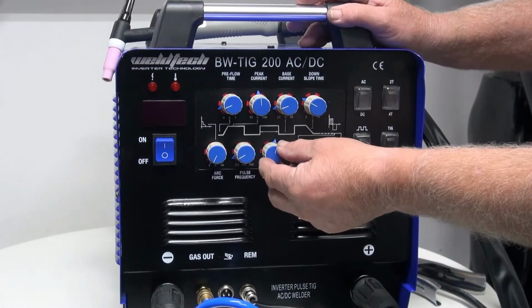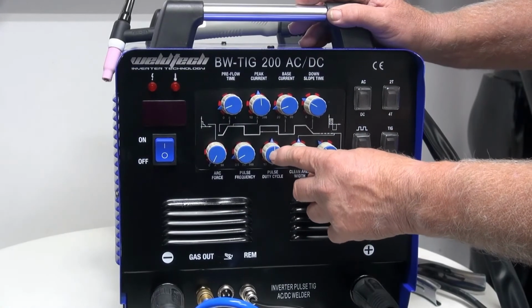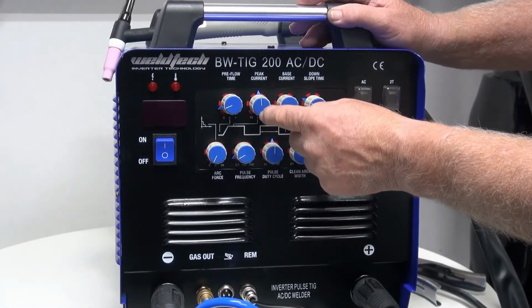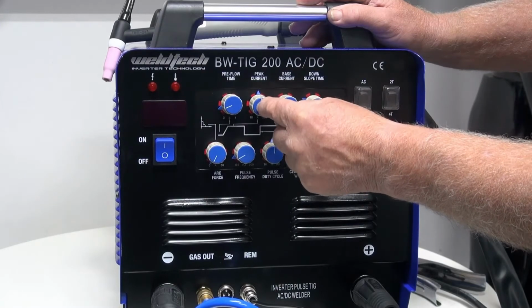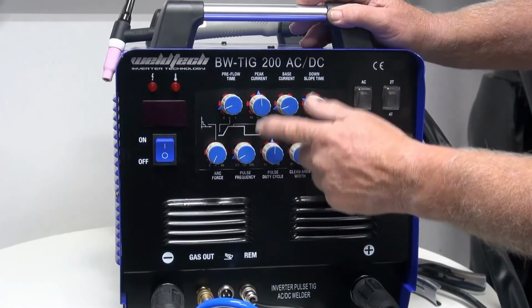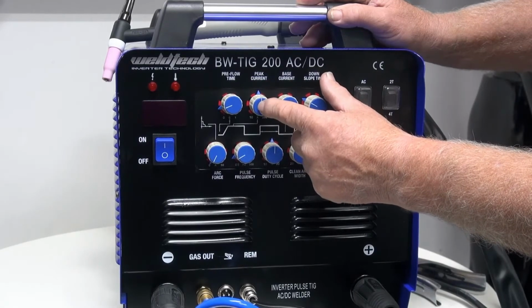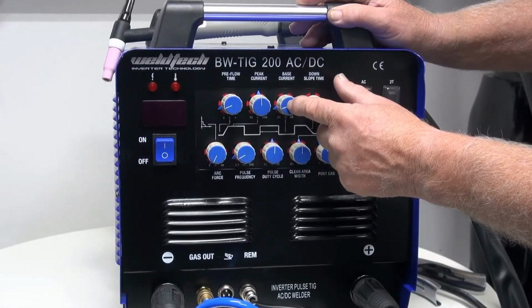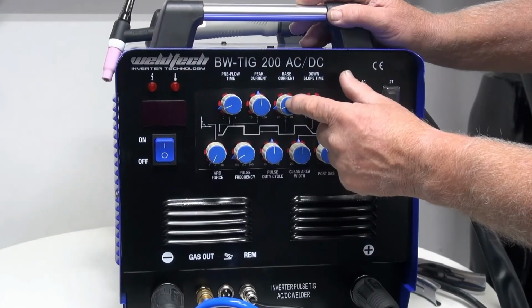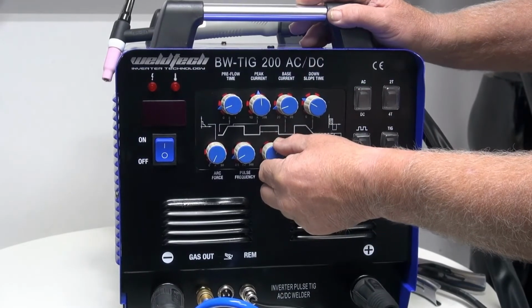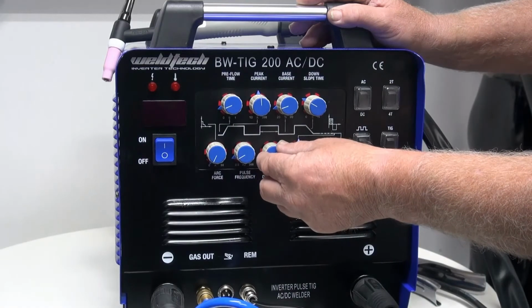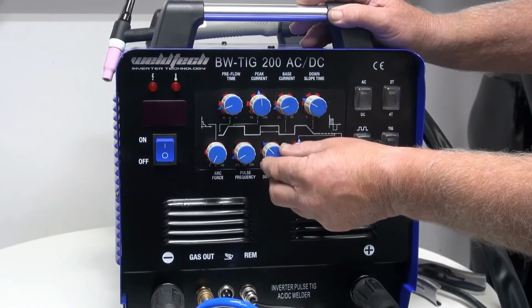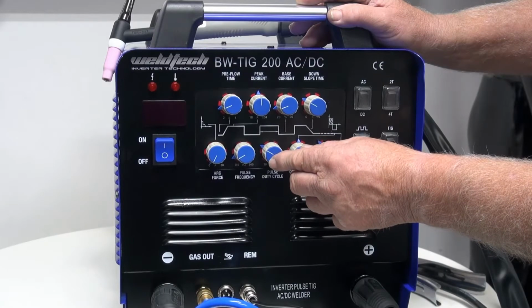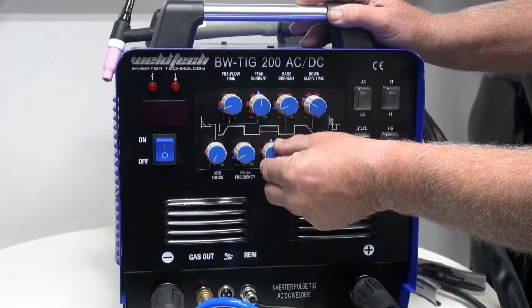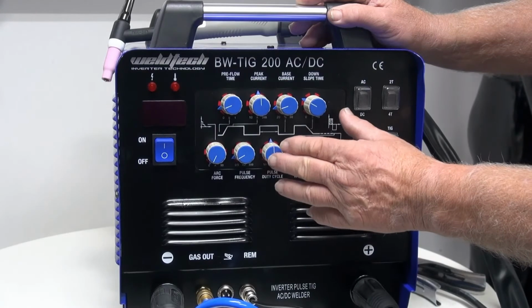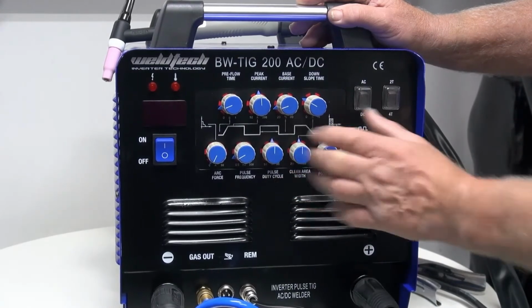The next knob along here is called pulse width. Pulse width determines how long on pulse it stays at the peak current. So if I have it set there, we have 50% at the peak current and 50% at the base current. This changes the penetration into the workpiece, or we can control the amount of energy going into the workpiece with the pulse. My theory is start at 50%, and when you get used to pulse, then play with it.